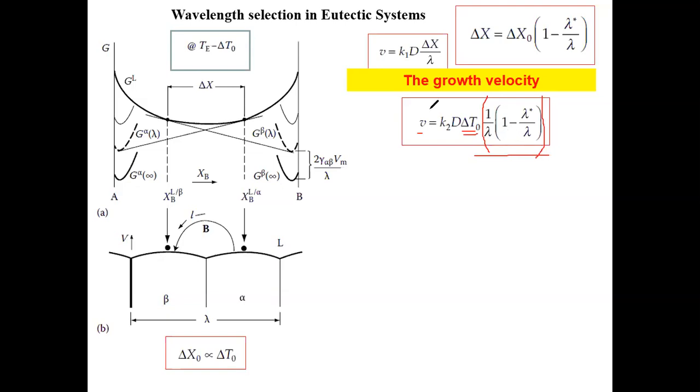This relation. Where have we seen this before? For the nucleus case, we also had the instability. We have a planar interface, and suppose that we have a small bump on this interface, which is characterized by a tip radius r. We showed that in those cases, the growth velocity of this bumpy interface also depends on r with a very similar relation to this one.